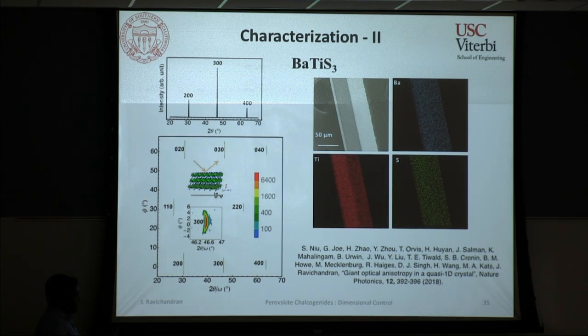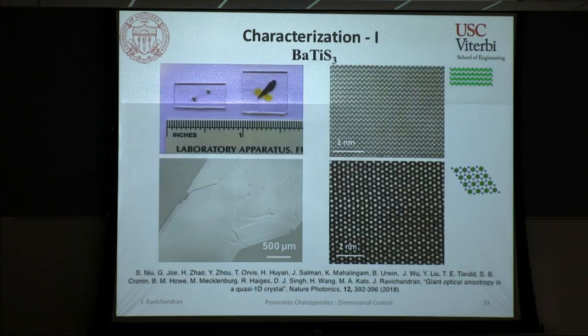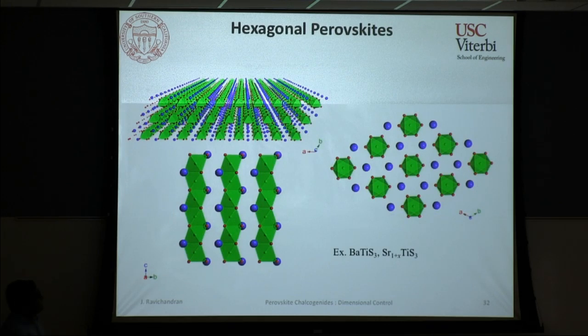Okay, so if you have a 1D chain compound with the A-axis as the normal axis, which means you have the B-axis in the in-plane somewhere. Now that means that if you take your system and rotate it by 60 degrees along this A-axis, you should be able to access the B-axis. Okay, so let me show this here.